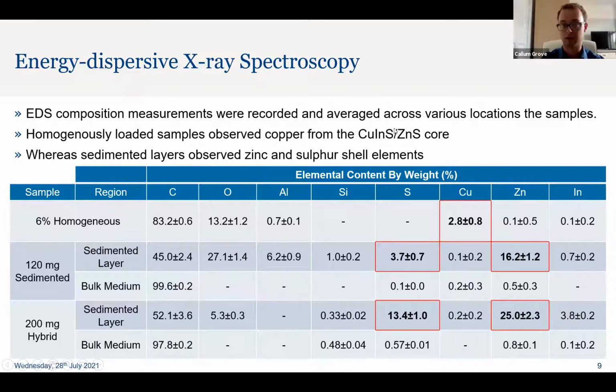In this kind of schematic, we'd have half copper and half zinc for every sulfur. And so you'd expect it to be around 3% copper, 3% indium. We didn't really see much indium, but copper suggests that there were quantum dots consistent with what we were expecting. And then the sedimented layers here are pure shell. So zinc at about 16% by weight versus sulfur about 4%. Converting these to atomic percentages, that's about 4% zinc and 2% sulfur, which sounds relatively low compared to a back of the envelope calculation for how concentrated the sedimented layers should be. They should be about 20%.